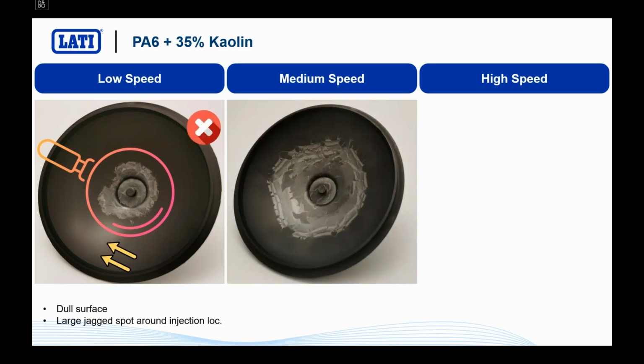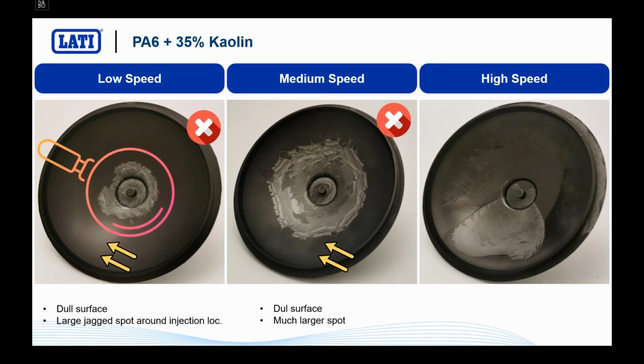The situation is, of course, somehow improved around the edges by increasing the speed, but you can see how it got worse, extremely worse, close to the injection location. You have a very bad looking spot and a dull surface as well. If you increase speed, you have some kind of improvement, but you cannot actually say that you are satisfied with your design of experiment. You still have a bad looking part.